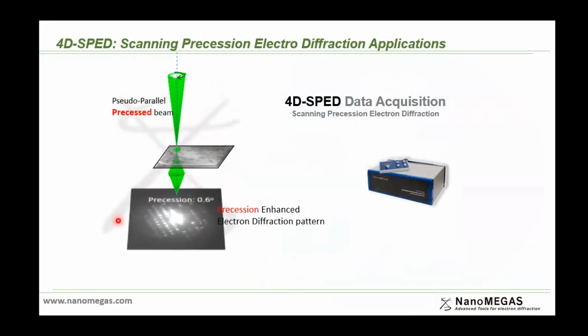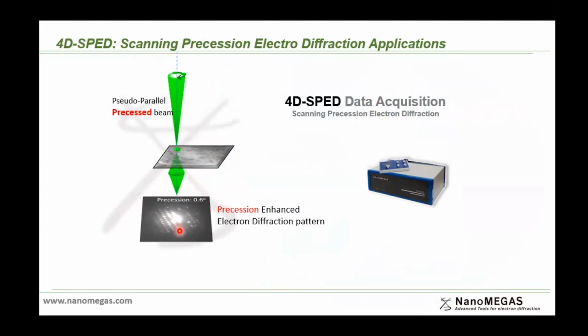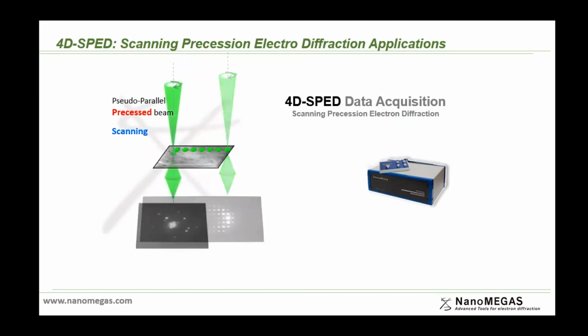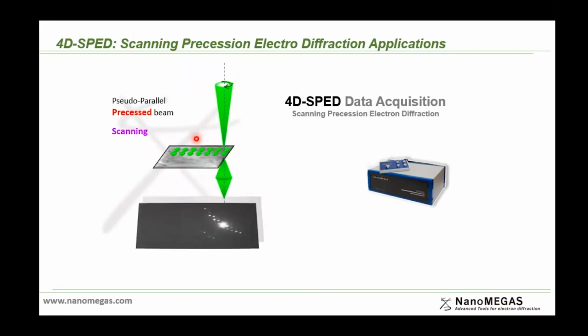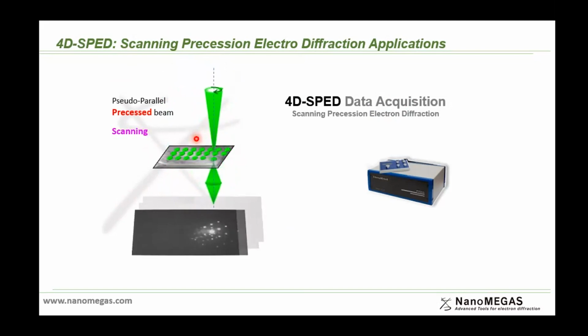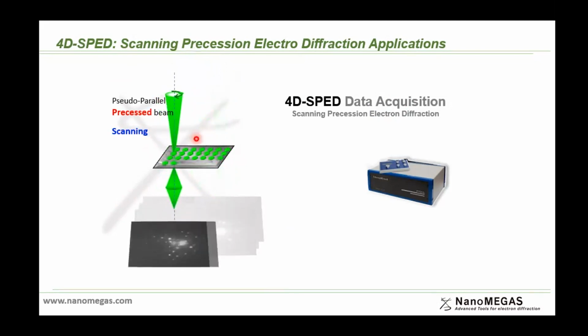And as we have this precession, we start scanning the sample. So we scan the sample, and for every point, we collect one diffraction pattern. So you can collect thousands of diffraction patterns, and then all these diffraction patterns can be used depending on the application that you want to use, okay?